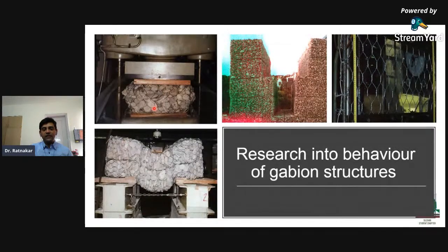So this is what you see, a Gabion of double twisted wire mesh, which is formed as a Gabion in which the stones were filled and they were compressed under compressive stress. And of course, this is a shear test where we are applying a load here, and there is a shearing happening at these two edges. So this is the first phase of the test where the compression and shear was done.